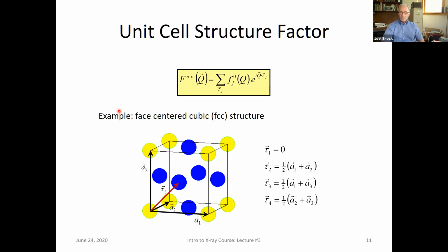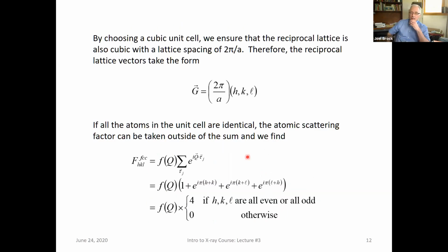So let's start with the crystal, for example a face-centered cubic structure here, where there's one set of atoms at the corners and another set of atoms on the faces, and I can write my unit cell so that I just keep repeating this group of 4 atoms over and over again. If I translate it over to this corner, I get the next unit cell. If I translate up here, I get another one, and so on. So I can recreate my whole crystal by repeating this little unit, these 4 atoms: the 3 face atoms and the 1 corner atom.